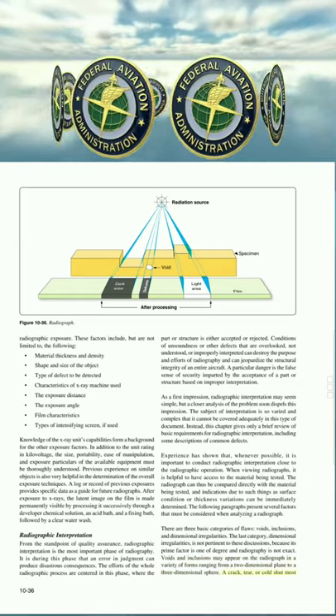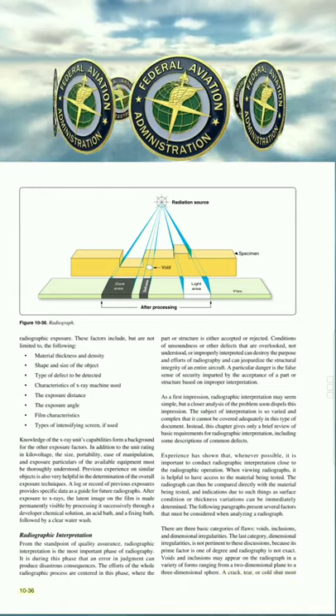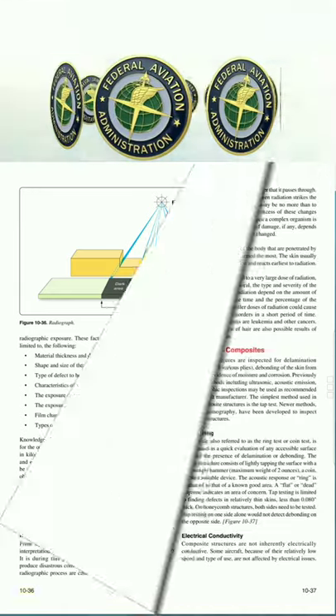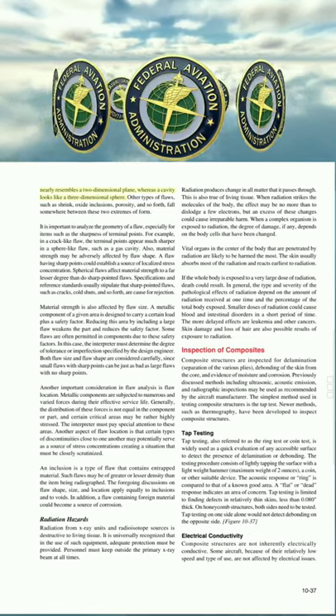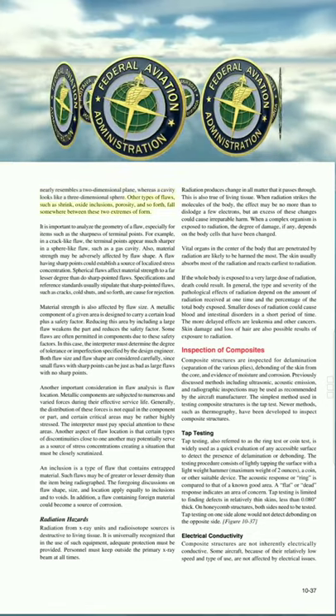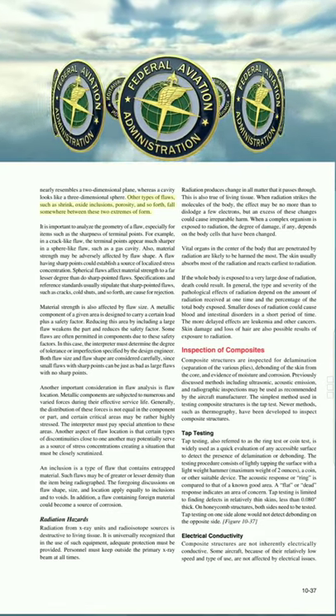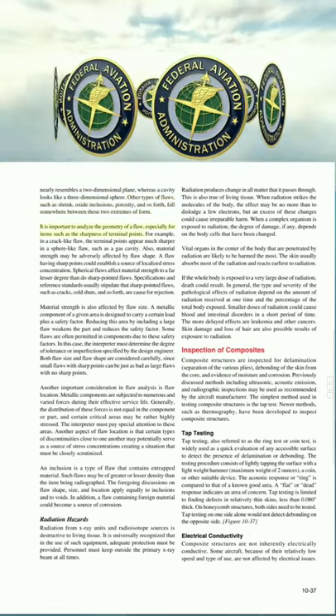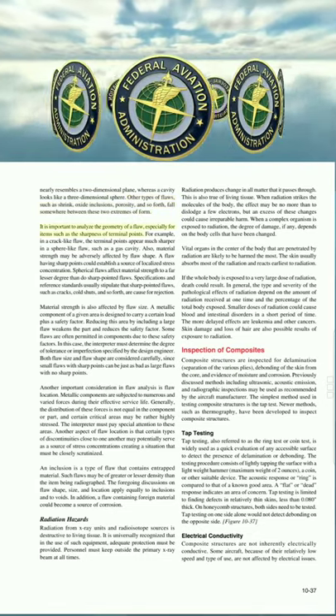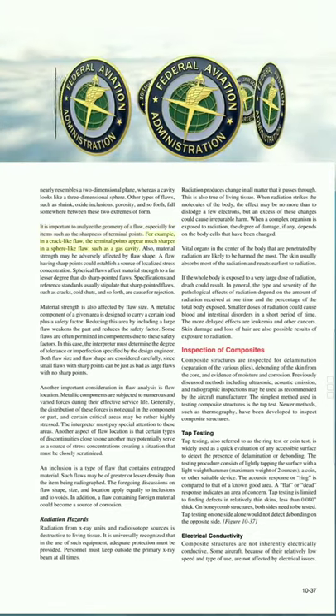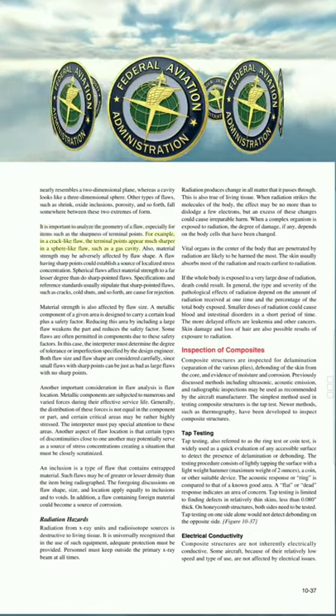A crack, tear, or cold shut, figure 10-36, most nearly resembles a two-dimensional plane, whereas a cavity looks like a three-dimensional sphere. Other types of flaws, such as shrink, oxide inclusions, porosity, and so forth, fall somewhere between these two extremes of form. It is important to analyze the geometry of a flaw, especially for items such as the sharpness of terminal points. For example, in a crack-like flaw, the terminal points appear much sharper than in a sphere-like flaw, such as a gas cavity.